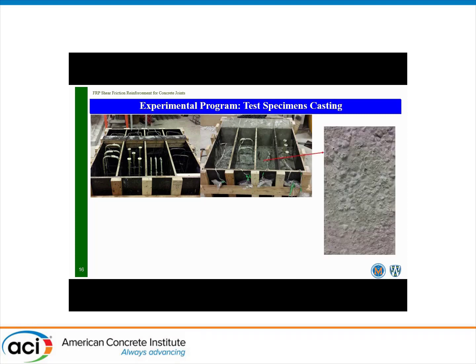At all times, we didn't pay any special attention to the preparation of the contact surface. We kept the contact surface, which is the top surface of the bottom specimen or the bottom surface of the top specimen, as cast. We don't prepare any special roughness or special preparation, and we kept it the same for all specimens.